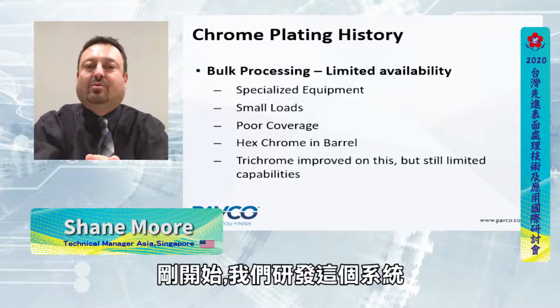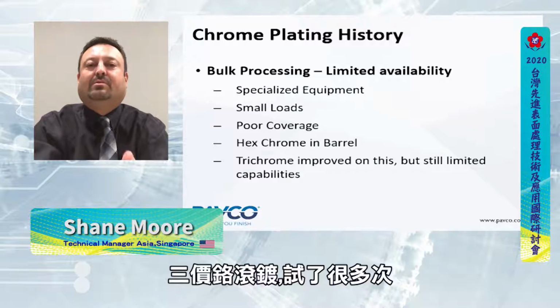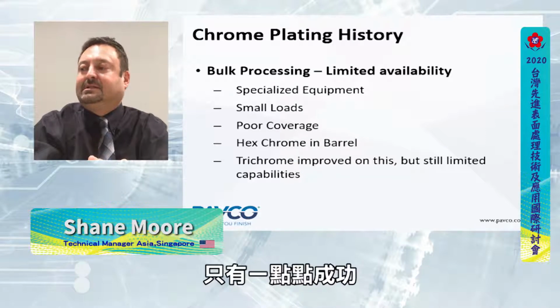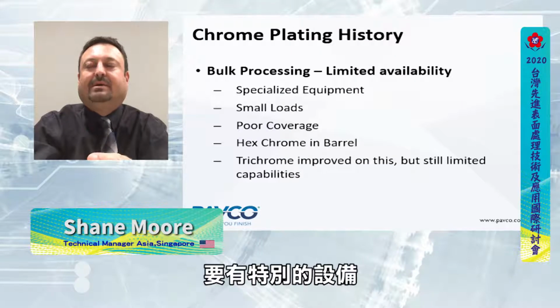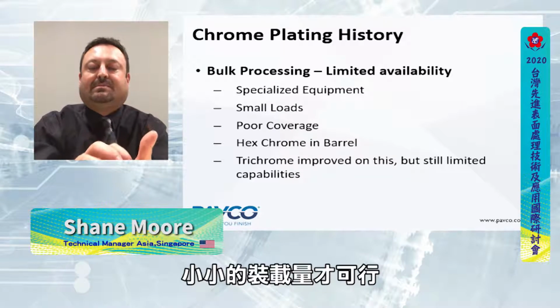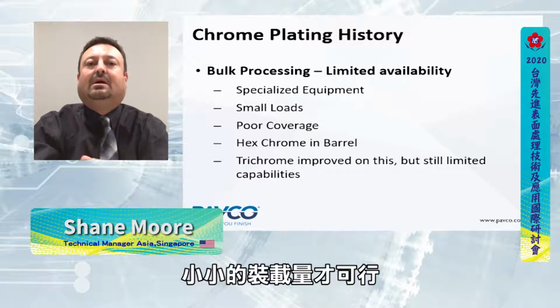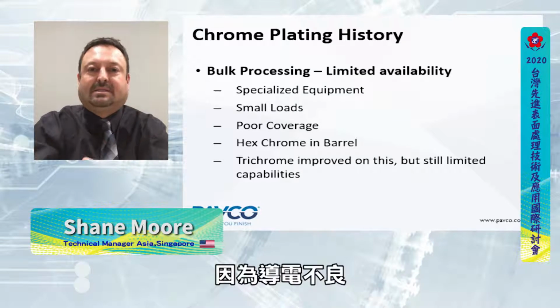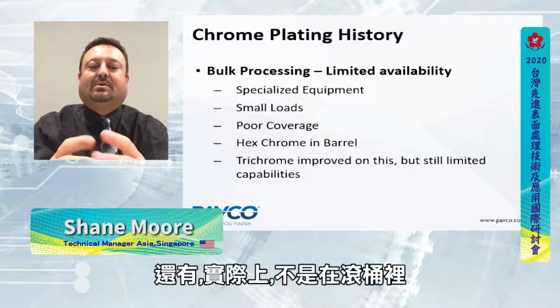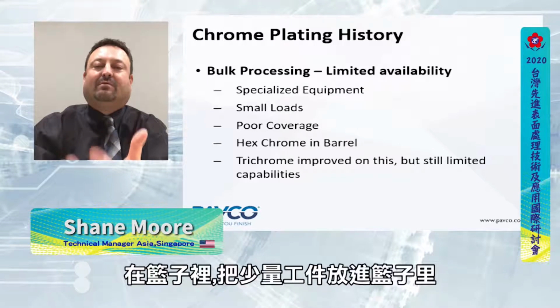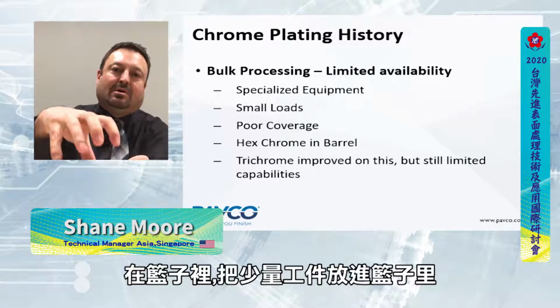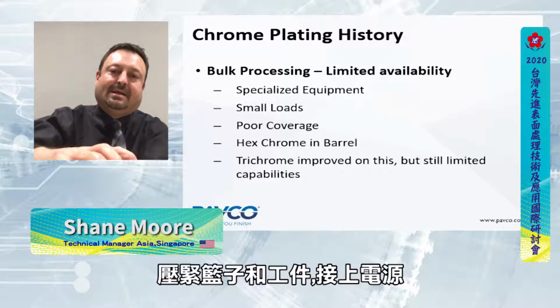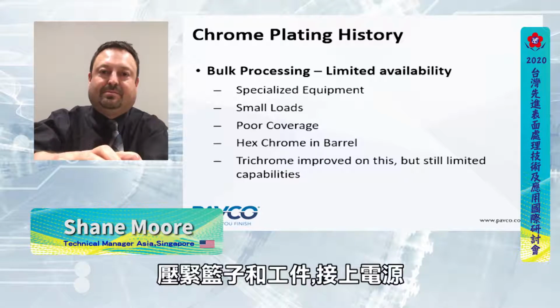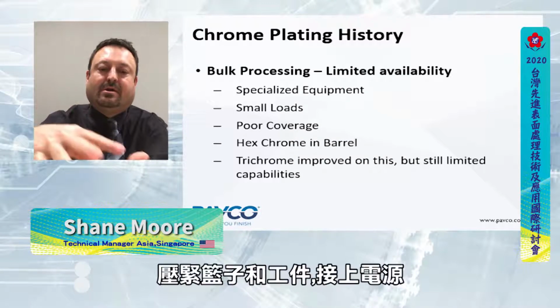So in the beginning, where we were able to develop this new technology, trivalent chromium in a barrel had been tried many times with very little success. You had to have special equipment. Only small loads were possible, just because of the breaking contact. And it wasn't even a barrel, it was actually more of a basket. So you would put this small load of parts in, and then you would tighten down the lid to the basket onto the parts, and then you would apply current.